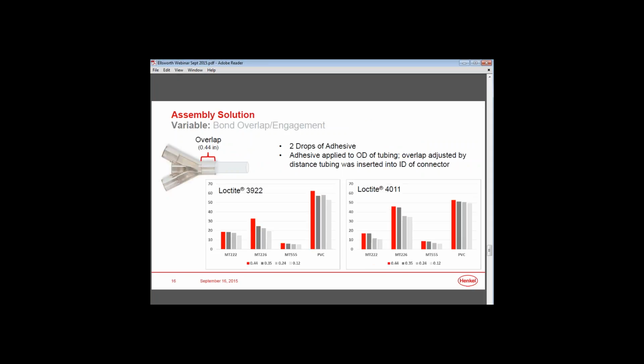So the next thing we wanted to look at was the overlap. So how far is the tubing being inserted into the connector? As I had mentioned, for all the testing prior to this, it was the 0.44 inch overlap where the tube was inserted all the way to the end. So for this series of testing, we adjusted that back to make a smaller overlap, still using the 2 drops of adhesive in the standard slip fit gap. And you'll see here that there wasn't a huge change or effect based on the overlap on the testing that we have here.